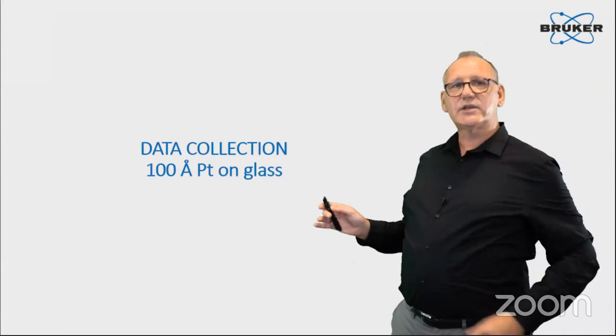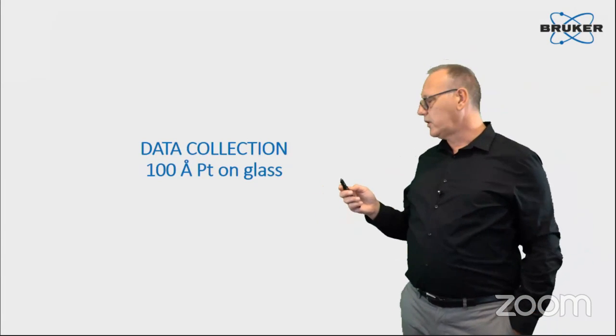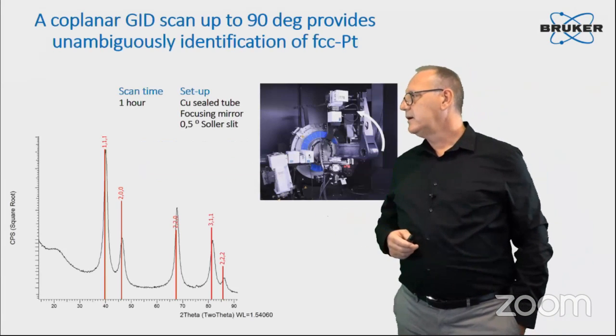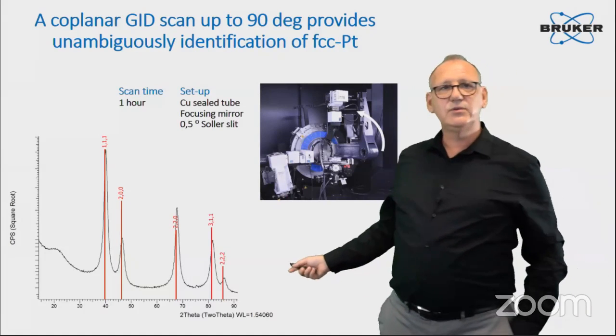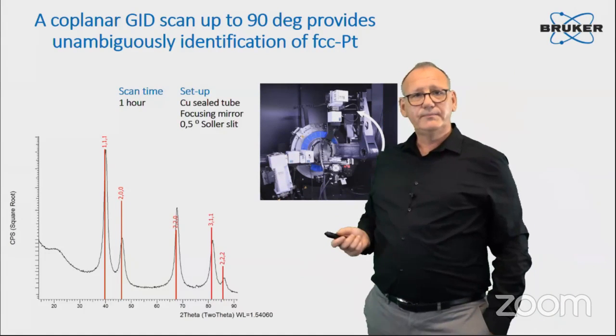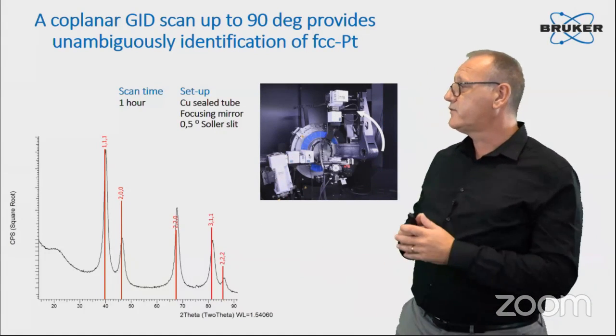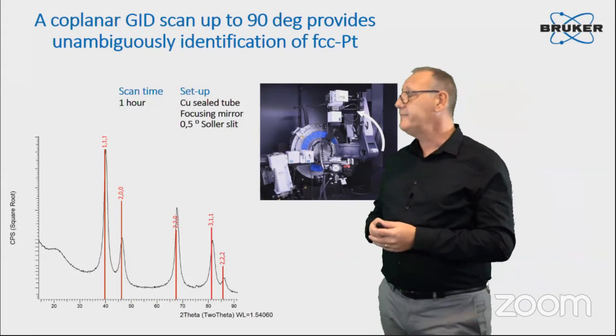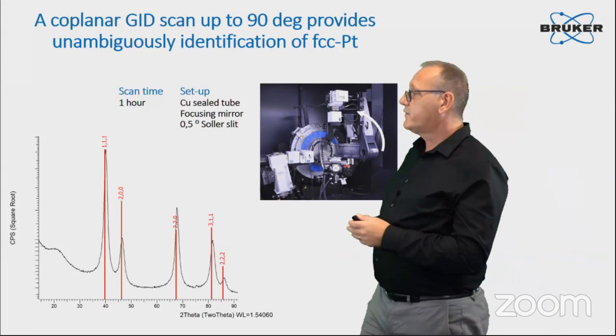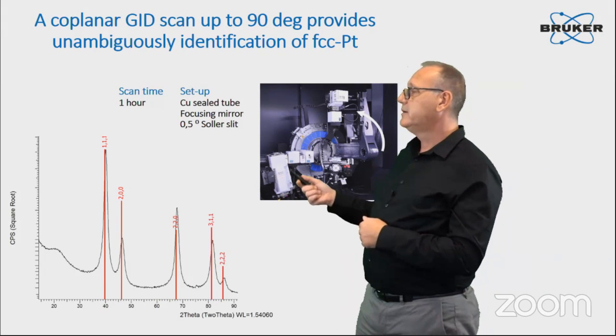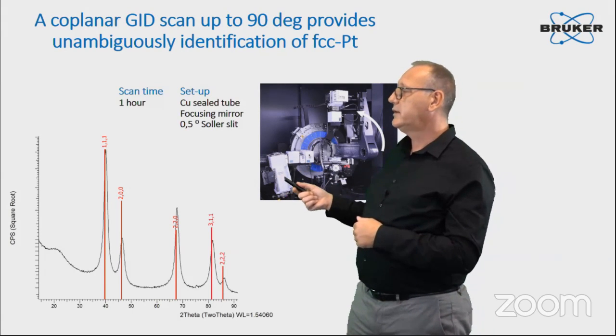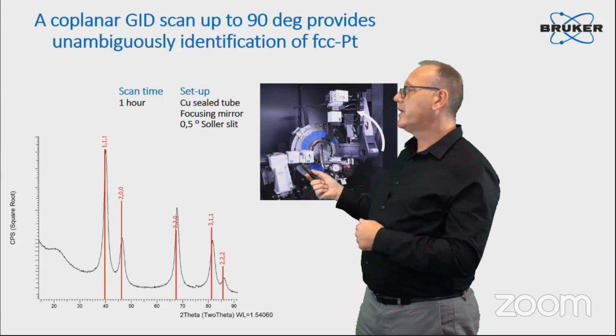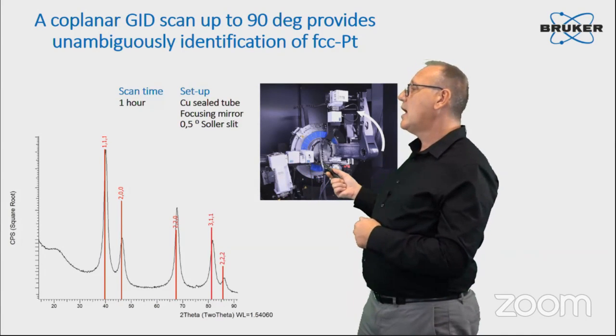So, data collection of 100 angstrom platinum on glass. This is the kind of data quality you can get within an hour, which is, I would say, for grazing incidence diffraction, a reasonable measurement time, using this configuration. We have a standard sealed tube here, used at 1.6 kilowatt. We have a focusing mirror that helps us to refocus as much intensity as possible on the sample surface.